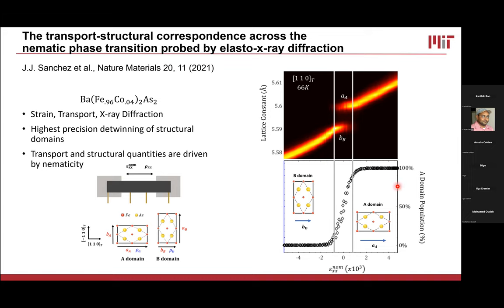So basically, under compression, I'm fully in the B domain. And with tension, I move fully into the A domain. And at a middle strain, I can smoothly switch between the two domains. And one thing that is really great about using X-ray diffraction to monitor the strain detwinning is not only am I getting information about the domain composition, but I can also look at the lattice constants.